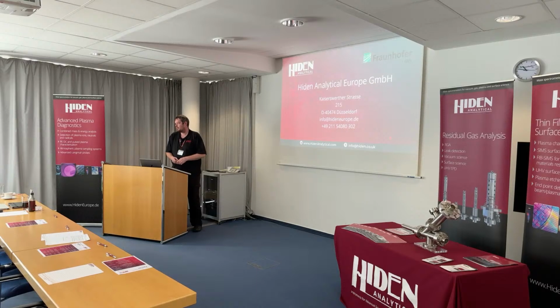What are the options to adjust the system to vary the distance of the EQP to the source? We have a standard test routine, so when we're testing it to send out to a customer, we try to position the EQP in the same position so that we can use various measurements as benchmarks to make sure it's performing properly. That's the main function of that chamber. But if we had a special request, we could fit a Z translator to it and position it differently.